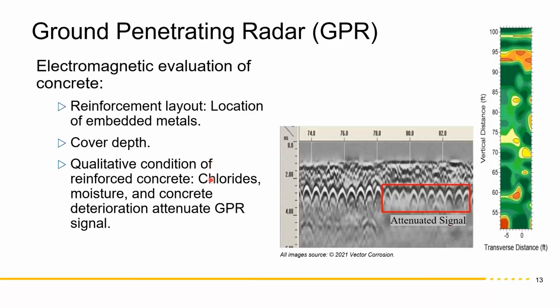Whenever you have chlorides or moisture or corrosion products like rust in the concrete, that makes it conductive and that attenuates, damps the signal. And that's the area where corrosion is probably happening. So that's shown here, or you can just simplify it and take the amplitude of these areas and create these heat maps, and lower amplitude areas like these red areas are where the corrosion is happening.